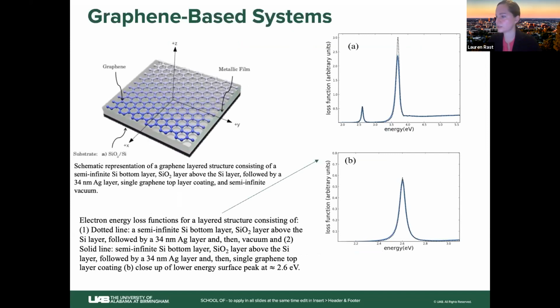Okay, so let's look at some of these results. In this example here, what I have modeled is a graphene layered structure. We have a semi-infinite silicon bottom layer and then a silicon dioxide layer above that, which often happens during the fabrication process. You get a thin layer of silicon dioxide. And then a 34 nanometer silver layer, 34 nanometers because that's the nominal size from the literature. And then a single graphene top layer coating, and then above that, vacuum.